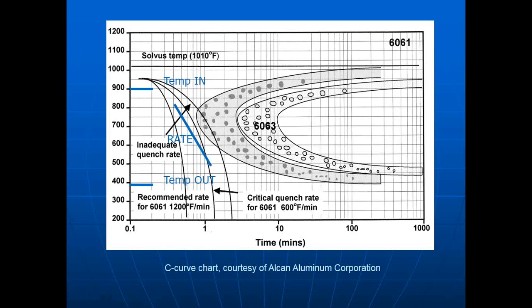Again, in discussions with your customers, they may say, well, but we want it a lot colder than that coming out of the quench. And the reason is all of the lineal needs to have made it to below 400 degrees. For a thick shape, if you're cooling only the outside in a water quench, the interior could be much hotter. So your customer might say, I want it to be 175 or 200 degrees coming out on the outside, which I can measure, to make certain that the inside is below 400. So if you hear other numbers, that's the reason.